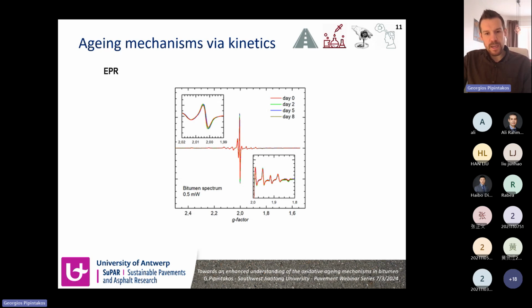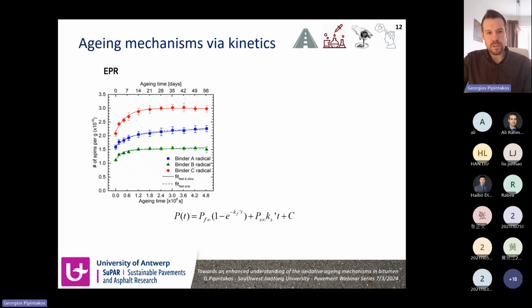What we observed by comparing these spectra with characteristic TEMPO solutions, which are solutions that give the number of organic radicals that you can have, is that in bitumen we can identify in the spectra both organic carbon-centered radicals, but also vanadyl porphyrin ions. And these two were then tracked over time. So their kinetics were plotted.